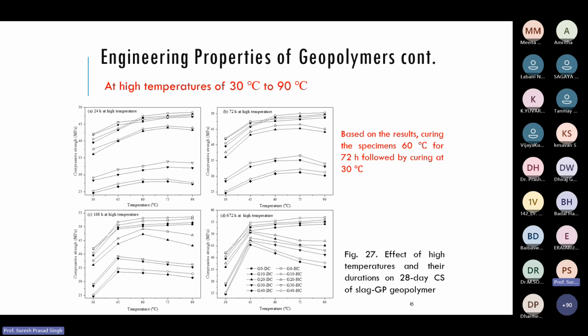So what it tells is that although it is told that at a temperature above freezing point it will harden, the most optimum value we get is at a temperature of 45 to 60 initial high temperature. And based on the study, you will see that the specimen should be cured at 60 degree for 3 days, followed by normal curing. So initial high temperature curing favors the high strength gain and high ultimate strength.